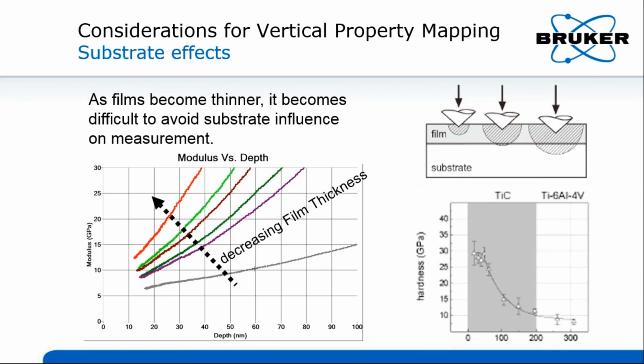When the applied load increases, the indenter goes deeper and deeper, and thus the deformation zone gets bigger and bigger. A substrate effect is observed when the deformation zone reaches the substrate. In this situation, the collected hardness and modulus are contributed not only by the film but also by the substrate. There is a transition of hardness and modulus changing with the penetration depth. At small depths, the film properties dominate, and at large depths, the substrate properties dominate.